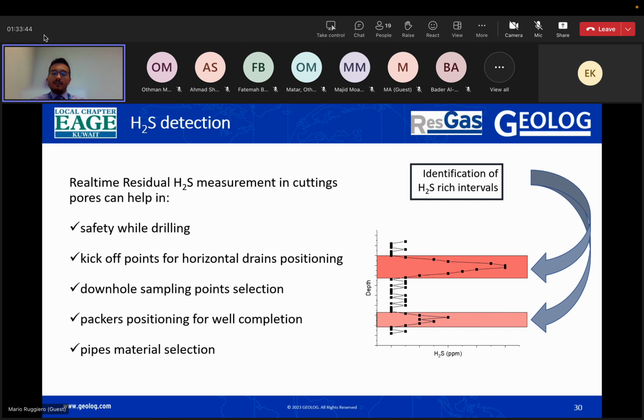So we can grind the cuttings and measure the residual hydrocarbons inside the pores and detect H2S. This, of course, is very, very helpful because you can help in well completion and in pipe material selection, because you may not see any H2S because of scavengers, but if H2S is present and you don't correctly plan your completion, H2S, you know, is deadly, but it's also highly corrosive, so your well completion could be a problem.